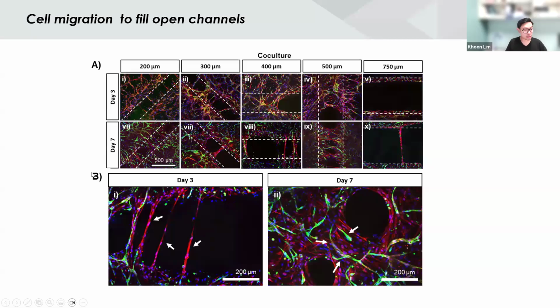The other thing that we found in terms of printing is also looking at the architecture and how architecture is going to affect vascular formation. So in this case, we're able to print constructs where you have channels of 200 microns all of the way to 750 microns. And you can see here from day 3 to day 7, if you have any open channels that are less than 500 microns, by day 7, you can see that the channels are now already filled with cells, right?